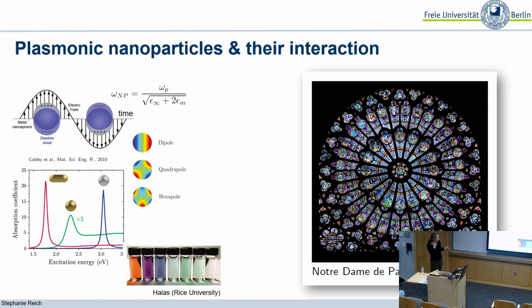So the nice thing about these plasmon resonances is that they are widely tunable, for example, by the material that you use. Here is a comparison between the absorption coefficients that you would get for a gold nanoparticle and for a silver nanoparticle. They are shifted because the dielectric properties of these two materials are different.